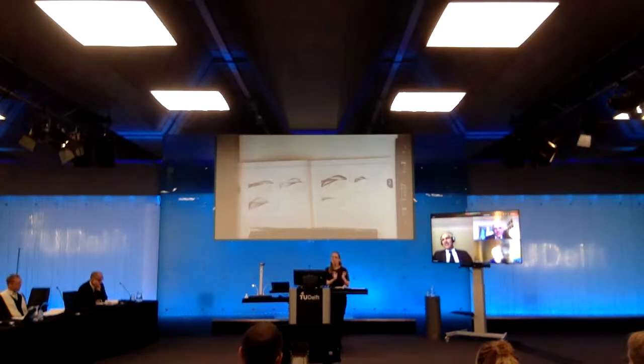So we were thinking about going again to the synchrotron. If you think about synchrotron experiments, what would you like to see upon charging of your system? Do you want to see changes in the crystal structure of the zinc oxide? Is that what you want to see? Yeah, those were the measurements we were thinking about. So in the XPS, we saw a difference actually. We saw a difference with the charged quantum dots and non-charged quantum dots, but we could not say whether this difference was intercalation or adsorption. So okay.